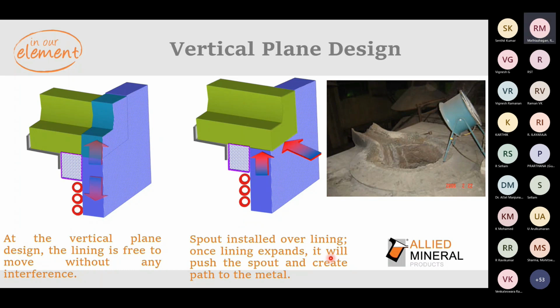So this is what I'm talking about. If you see the second picture, the arrow here indicates the crack over here and leads to a metal penetration, because when the lining expands and contracts, the lining pushes the spout up, while contracting, the spout stays still on the top, creating a gap over here, and the metal might penetrate here. This is a common scenario which we have seen in most of the foundries. So we recommend to do the spout first and then do the working lining.